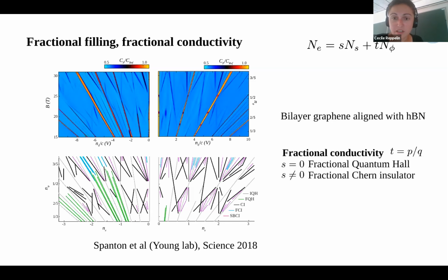second diagram here. And they can identify a lot of different combinations of S and T being zero, non-zero, fractional, or integer. So T, again, according to the Streda formula, as soon as you have an incompressible phase, T basically gives you the whole conductivity. So if T is fractional, T equals P over Q, then you have a fractional conductivity. And then if S is zero, basically no lattice effect, no superlattice effect, we call that just fractional quantum Hall effect. But if it's non-zero, that means that you've obtained your